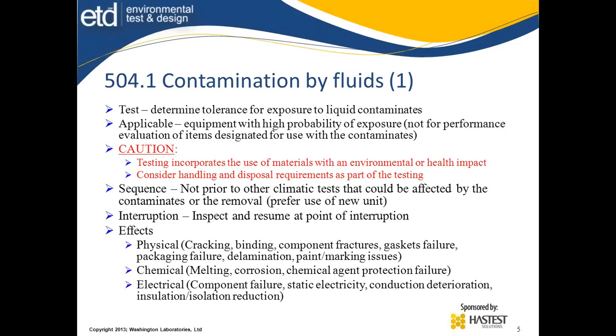Interruption of the test: you need to inspect it and resume at the point where an interruption happened. Normally the interruption is either an over-test or an under-test mode, and basically it's handled both the same way. Examine, see if there's things that you might need to replace or restart. Effects you can often see by contamination are physical, where you end up with cracking, binding, fractures of components, gasket failures, packaging failures, the box falls apart.